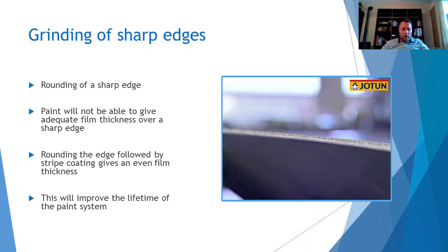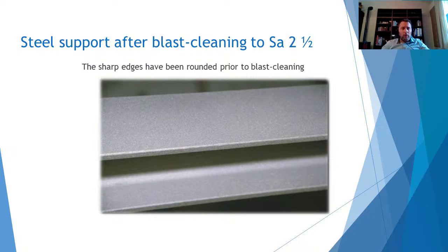Here we have a picture of a piece of steel blasted to the cleanliness grade of Sa 2.5. You can see in the picture that the sharp edge has been rounded prior to blasting. I must emphasize this point: there is no coating able to protect a sharp edge. So the steel preparation is strongly recommended.